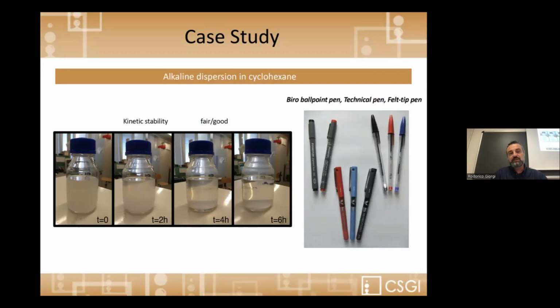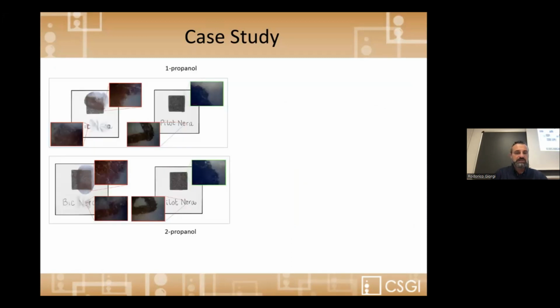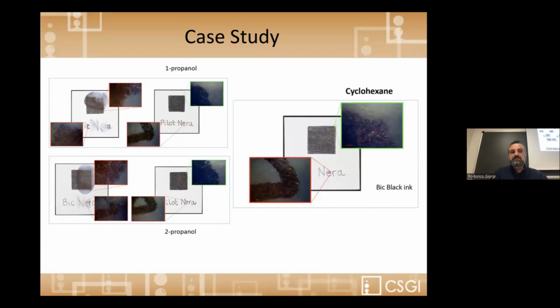Working with cyclohexane prevents the risk we might have working on some specific inks with alcohol. For example, in this case, we have that black ink with a trademark Pilot is not sensitive to propanol, 1-propanol or 2-propanol, and this means that we can use the original formulation. But when we have a biro ballpoint pen like Bic, in that case, alcohol used by dropping could be not compatible. In the same condition, cyclohexane is perfectly inert.